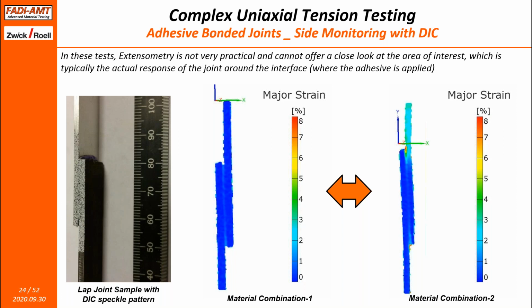And you can see obviously on the right how the material itself, the substrate itself, is deforming. And that means we have a relatively weaker substrate, which is leading to a peeling effect that causes failure in a totally different mode than the one that you see on the left-hand side, simply because the stiffness of the joint is much higher, and therefore you can see the interfaces building strains without much deformation in the actual substrates, and therefore you see totally different failure. Again, on the right-hand side, there is a peeling effect that starts from the top to the bottom. On the left, it's a sudden failure of the actual adhesive layer. And again, that's something that is impossible to do with conventional extensometry.